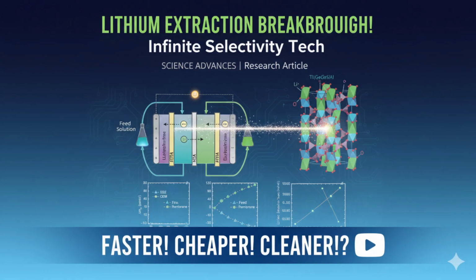But with this electrochemical SSE approach, you're applying an electric field to selectively drive only the lithium ions across. You're not wasting energy moving bulk water. Okay, so the specific energy consumption, the energy needed per kilogram of lithium extracted, could be much, much lower. Orders of magnitude lower, potentially, compared to pressure-driven methods for achieving similar separation goals, especially from dilute sources. That's what makes it so promising for making direct lithium extraction from these unconventional resources economically viable and, importantly, more sustainable. Wow, okay, that is a powerful advantage. Less energy means lower cost and a better environmental footprint.